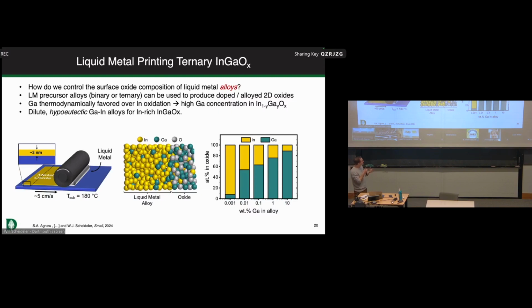But we have a solution, which is that we can control the concentration of the intrinsic oxygen vacancy defects in our material with aliovalent atoms like gallium. My student Simon's been working on this problem for a while, and it turned out to be a more interesting and more challenging problem than we thought initially. What he discovered is that gallium and indium, when they're on the surface of the liquid metal, are in competition to dominate that surface oxide. There's a lot of literature now on this because of the use of eutectic indium gallium in stretchable electronics. But the short story for what we observed is that you can use a very dilute alloy, down to the parts per million level, to be able to control this.